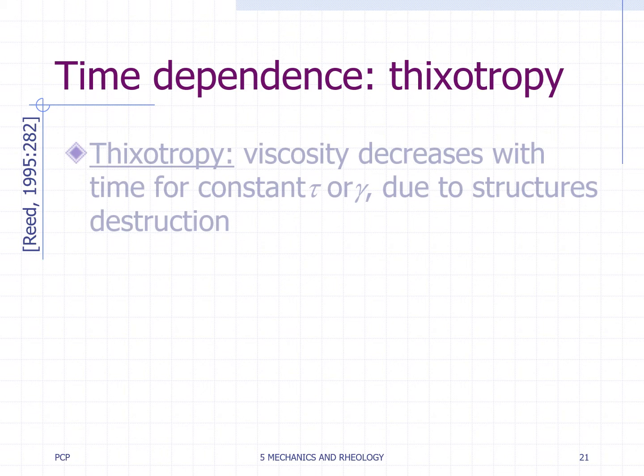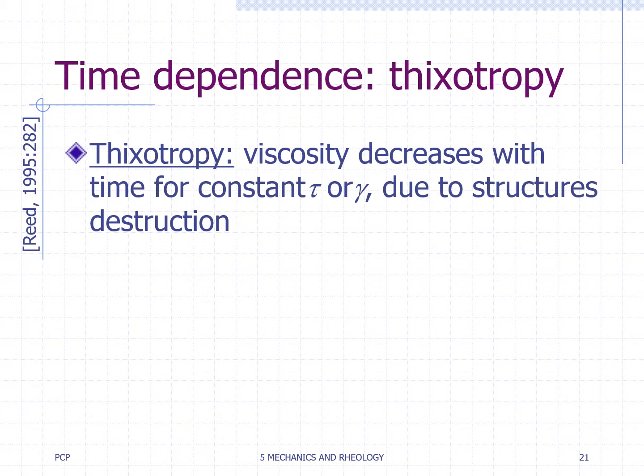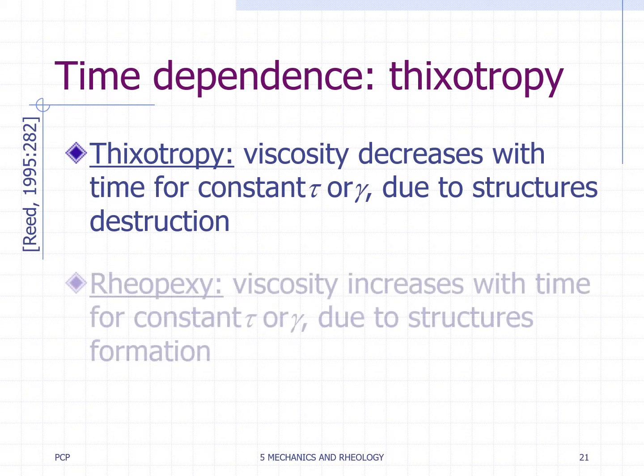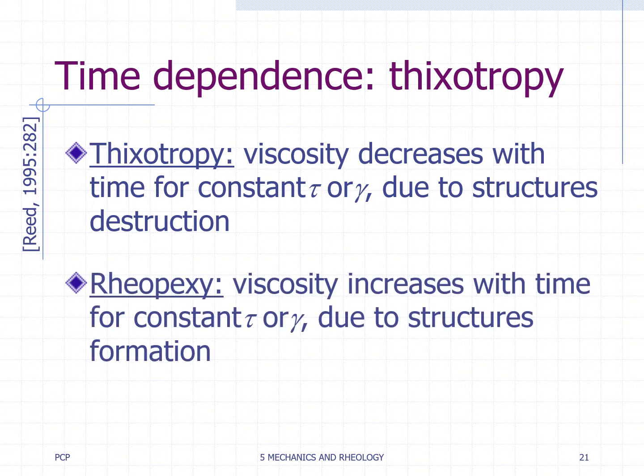This behavior, called thixotropy, is commonly observed for shear thinning materials, when the bonding of molecules or particles breaks apart with time during shear flow. A few materials exhibit an increase in viscosity with time when sheared at a constant rate. This behavior is called rheopexy and may be expected when agitation enhances bonding between structural units in the suspension.